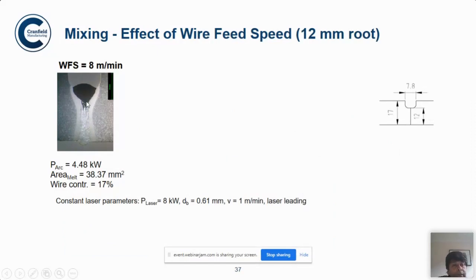So when you do laser welding, if the process parameters are not controlled, you create a molten pool at the bottom, as you can see here. Follow my mouse, which is done by melting of the parent alloys, and the arc process deposits the metal which remains in the top and it didn't penetrate. So this is not good, because these two parts can create a very highly graded structure. This particular experiment was done with duplex steel, actually, just putting chromium as a signature element to understand the performance or the response of the different arc and laser power sources for creating a proper homogeneous structure.